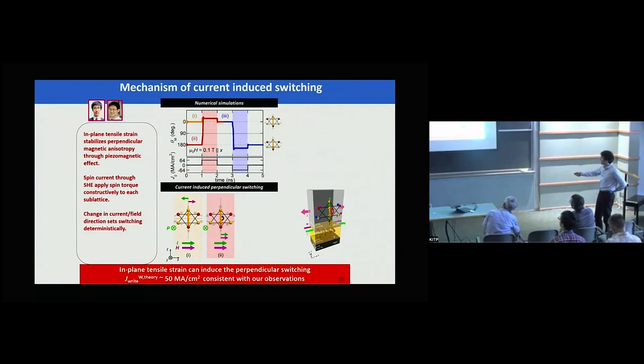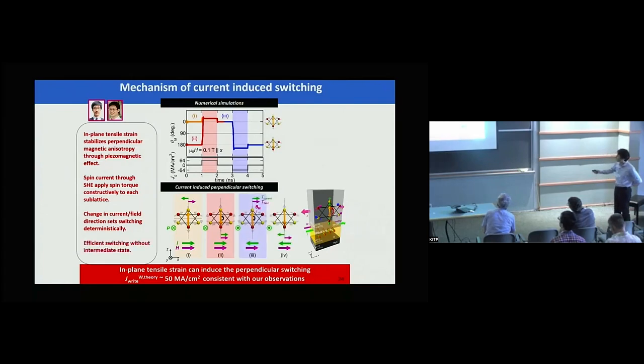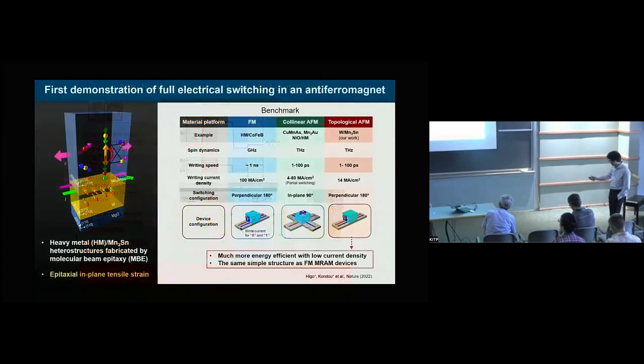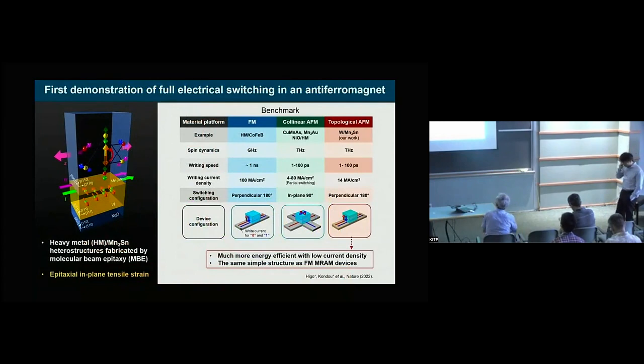And another thing is that if we change the polarity of the current, one can actually go from this initial state to the final state, and finally come back to the same original state, without going through any intermediate state. So that's actually different from the ferromagnetic switching. I would say this is a hypothetical statement at this point, and we hope we can see that this is proven by a time-resolved measurement. So this is an interesting comparison for future development of such a memory.